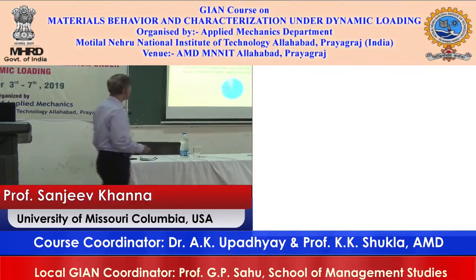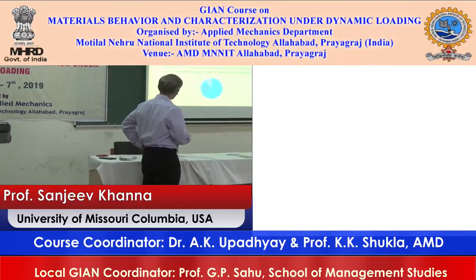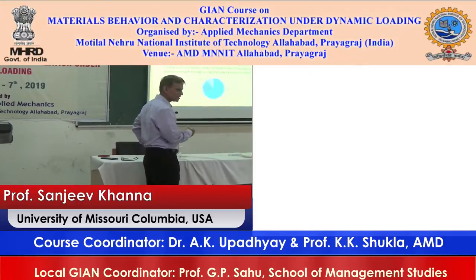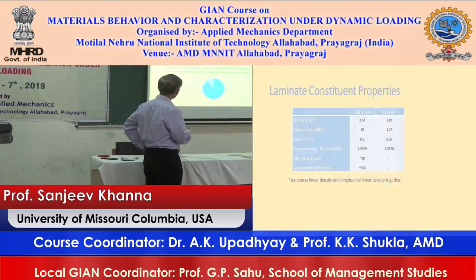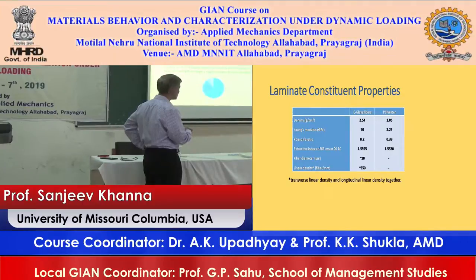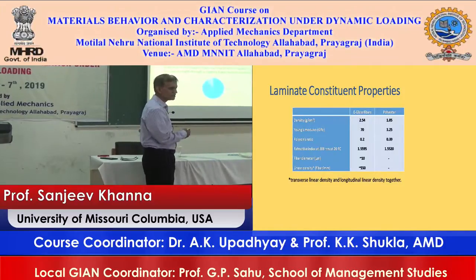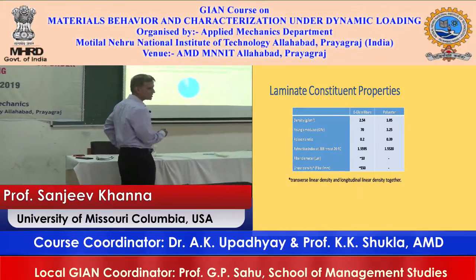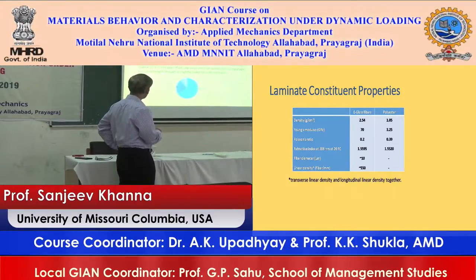If you can see here, in this one we used transparent E glass fibers. Polyester was the laminate, the matrix material, and we used tempered glass sheets. Now, polyester was selected as the matrix as it is very cheap. It's cheaper than vinyl ester or epoxy, and as comparable, tensile strength was slightly lower, tensile modulus.